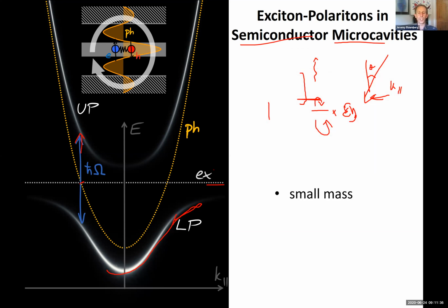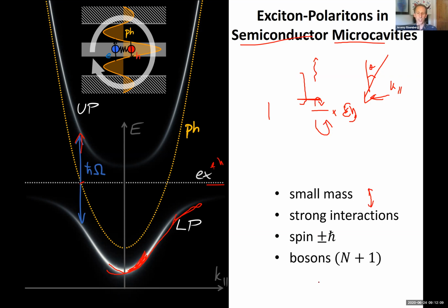So the first thing, although this is a particle which is an exciton, if you look at the shape of the dispersion here, it's extremely light. These particles are something like 10 to 100,000 times smaller than the mass of the electron. So they move fast, which is their photon aspect. But they also have this electron hole pair nature, so they're charged, so they have strong Coulombic interactions with each other. So this combination is really interesting in this particular system. They're also spin polarized, and they're also bosons because they're made of two bosons.